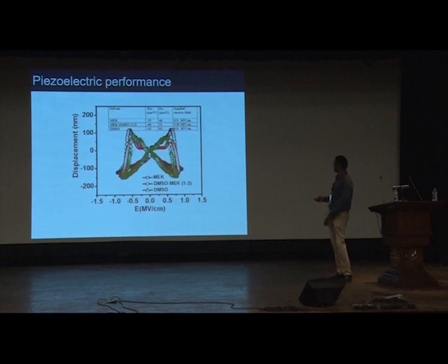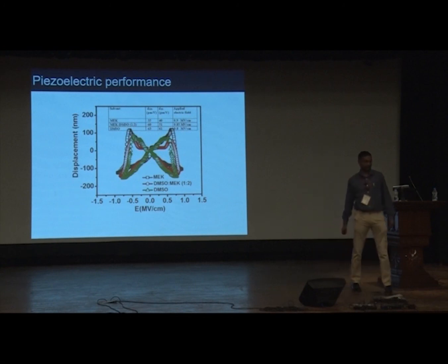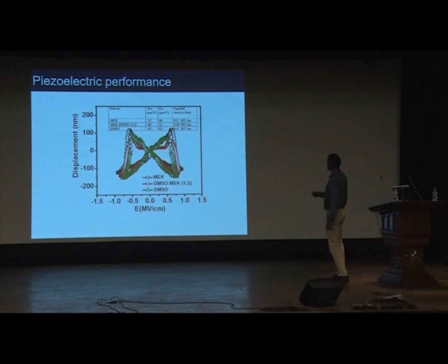And not only do you get very good fatigue performance, you have very high piezoelectric properties here. The single solvent piezoelectric coefficient is of the order of -35 to -40, but the co-solvent gives you a piezoelectric coefficient which is -60 to -65, which is reasonably good for piezoelectric energy harvesting devices, along with low coercivity. The coercivity is also smaller.